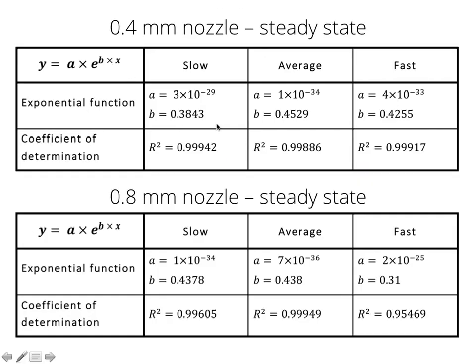The exponential functions are quite interesting to look at, especially the parameter b. The parameter b is around 0.45, you can see 0.42, 0.43 and so on. So the logarithmic slope is basically the same regardless of the nozzle size, except the fast one is kind of an outlier, as already mentioned. First of all, the fit is not that great, and also the logarithmic slope is not that high.